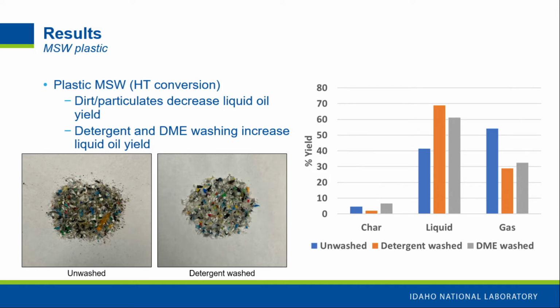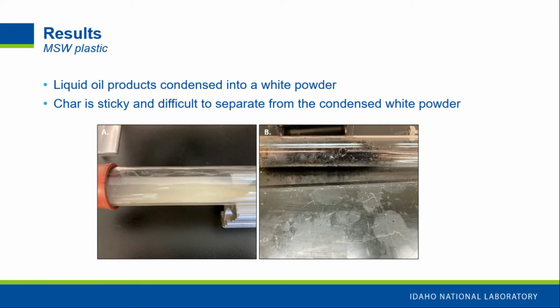And we found that in both the detergent and the solvent wash, we were able to increase our liquid oil yields. It wasn't without its problem, though, because our liquid oil products really quickly condensed into this white powder that's super difficult to separate from the char. And the char is very, very sticky, and it's just very difficult to work with and try to quantitate. And so this is something that we're working on troubleshooting now. So if anyone has any suggestions here, I know there's a lot of pyrolysis experts, we would be happy to hear what you have to say.